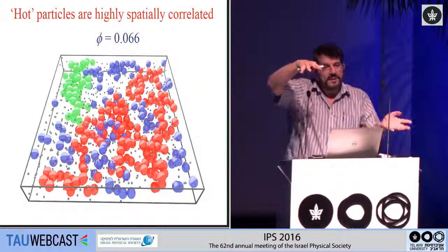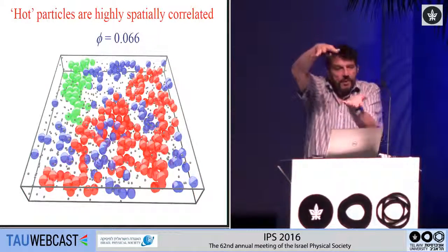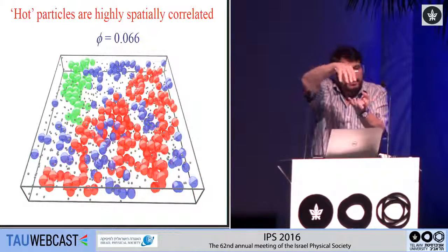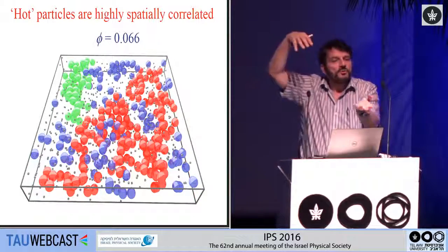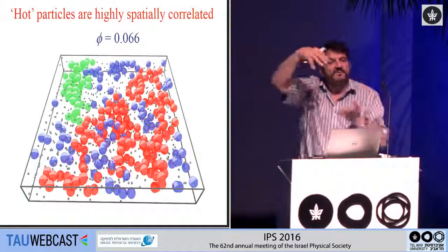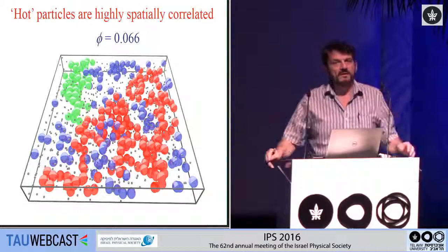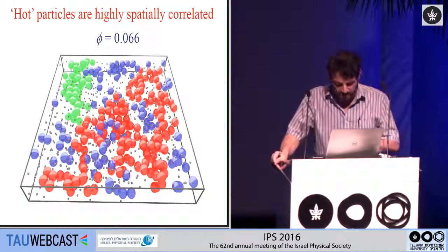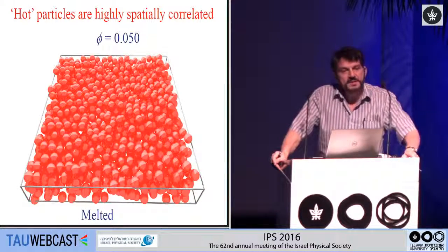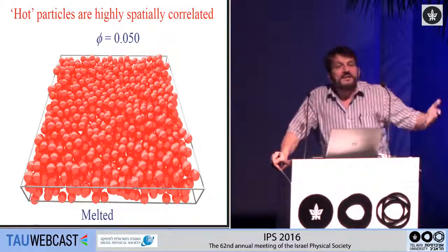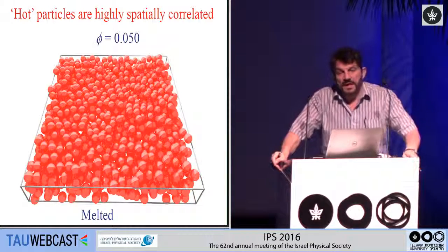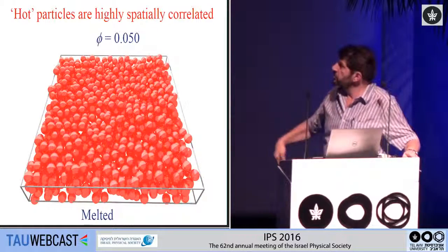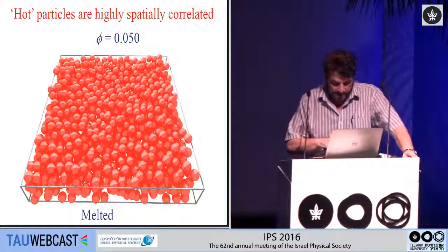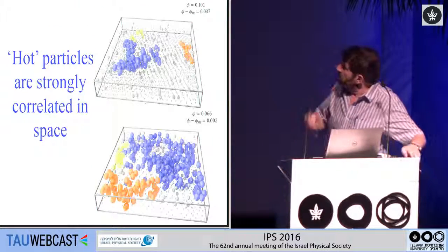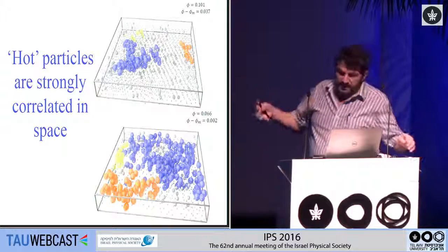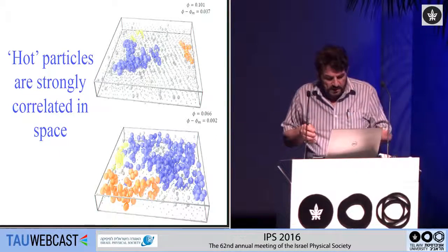So I like to think of this as a system where the particles are more or less stationary, but you have these extended regions, extended clusters of very hot particles, particles that are undergoing much larger fluctuations. Of course, if you look at the system when it's completely melted, then everything has a much larger fluctuation, and you don't see anything in particular. So the hot particles are strongly correlated in space, and we can start looking at the nature of this correlation.